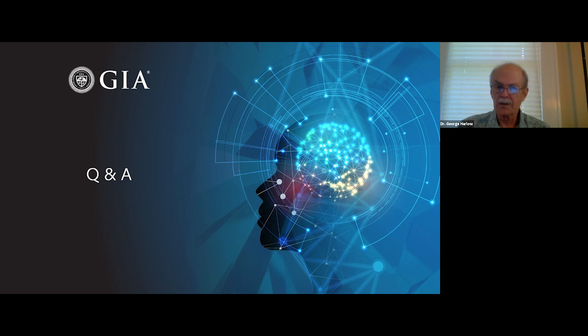And it is an intervalence charge transfer kind of color between iron and titanium, and often is more observable in the omphacite varieties than in pure jadeite itself. So those are really the colors due to replacements with other elements. The other thing, as Holly said, is that jadeite can be colored by staining.